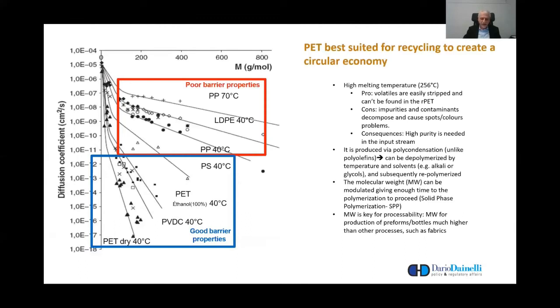PET is certainly one of the best suited polymers for recycling. And this slide shows why PET is so well suited. It is not indeed the only one, but it intrinsically shows physical chemical properties that allow easier and faster cleaning from any potential contaminants that might have polluted the bottle during the post-consumer phase. PET has a high melting temperature, over 250 degrees, which means that one can heat it up and volatiles are easily stripped, so that they cannot be found in the final recycled plastics.